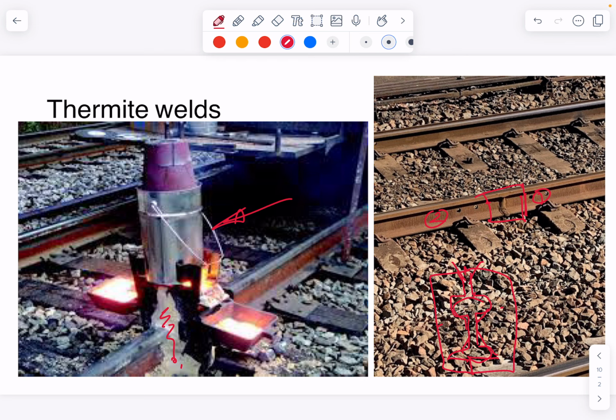Before they set off the thermite, if you see this happening at night on a railway, which is the only place you'll see it, they'll have a huge oxyacetylene torch warming the rails up to get it nice and warm so that it doesn't quench the weld metal too quickly and cause metallurgical issues. So you might see a big glow from some oxyacetylene torches as they warm the rails. They'll have the moulds ready to go. These are just sand, basically. They'll slap those on, mud them into position, light the thermite and stand back, and it'll dump its load into there. They knock the moulds off just with a hammer.